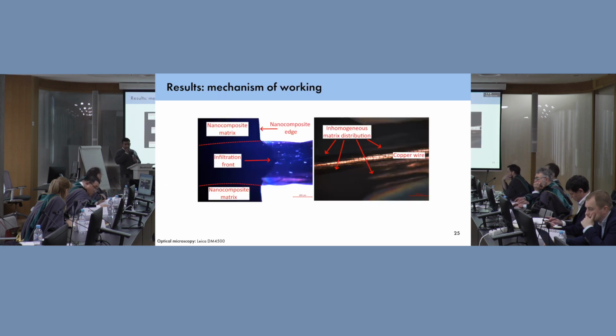Right, so we made our fibers, we see the effects of the diameter, we see the effects of sensitivity to different types of nano additions, and we needed to understand, okay, it's working, but why is it working? So we come to our microstructural analysis in this case. And what we did was first, obviously, we started with optical microscopy. So we took a single carbon nanotube fiber, we added a droplet of our nanocomposite matrix, and we noticed a